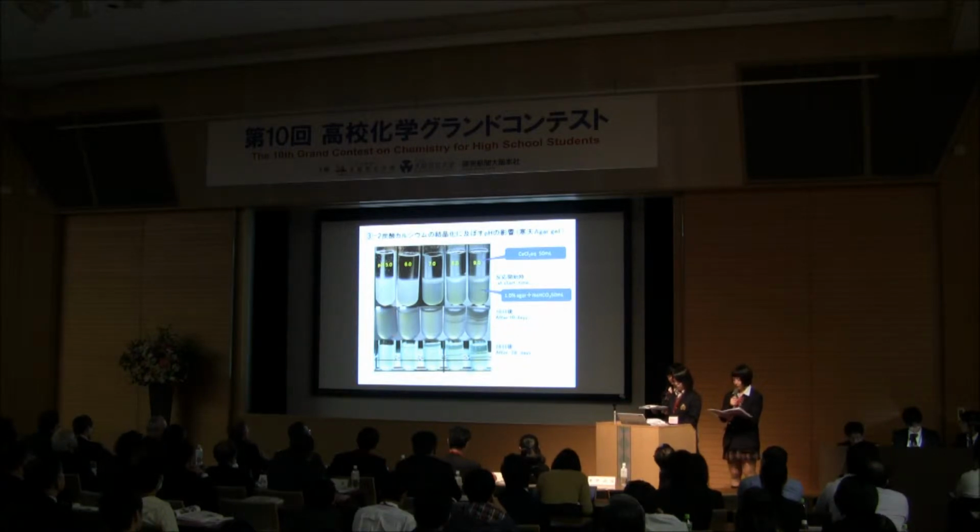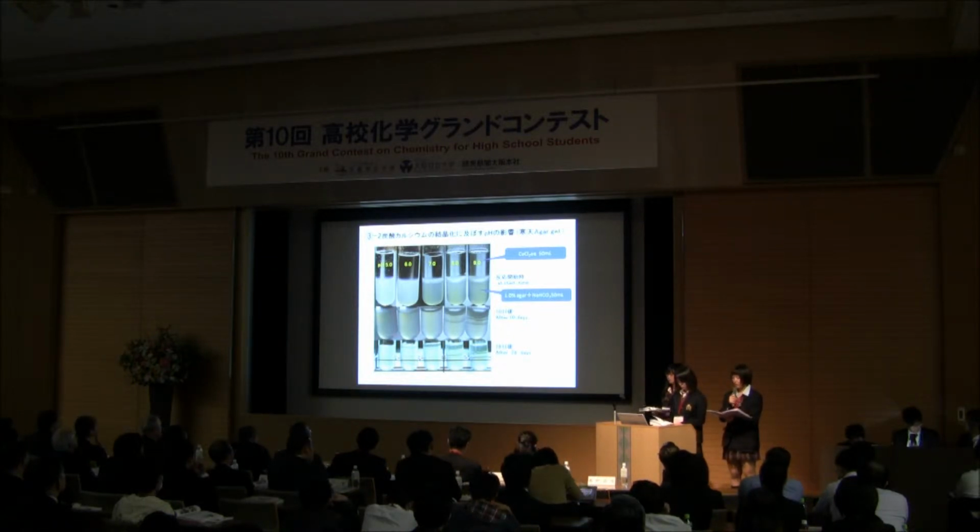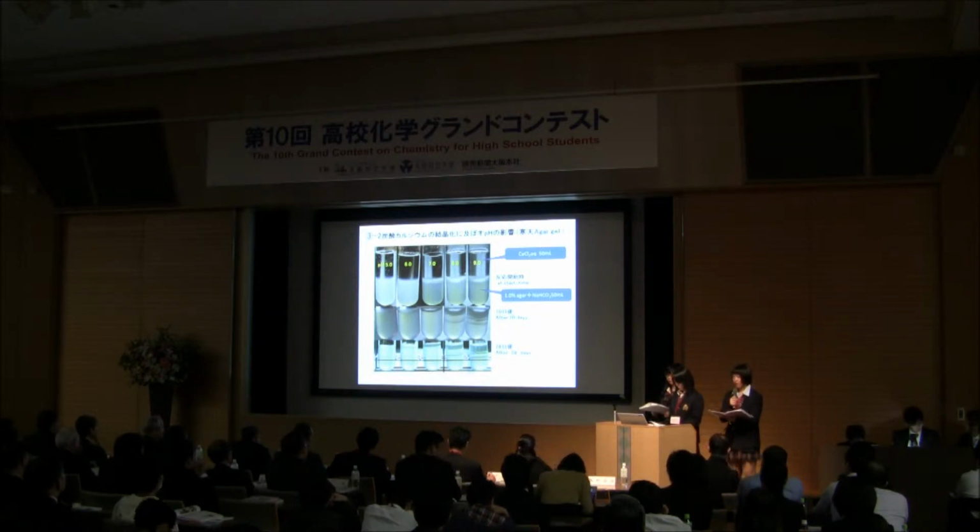We thought that to form big calcium carbonate crystals, pH 8 and 9 levels would be too high, because the concentration of CO3 2- ion is high, so calcium carbonate deposit appears quickly. Therefore, we concluded that pH 7 level is the best to form big crystals.